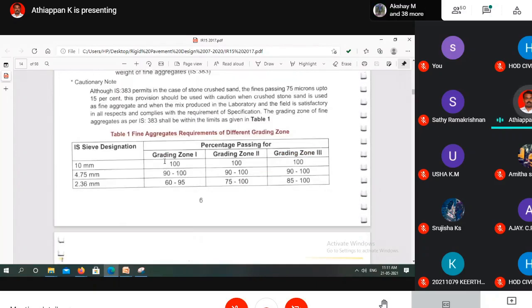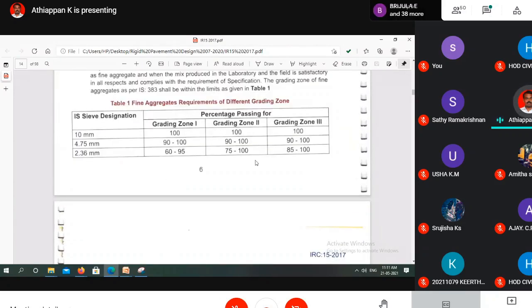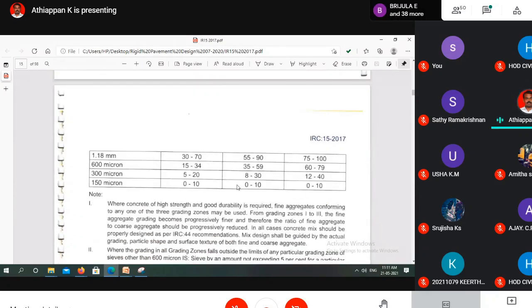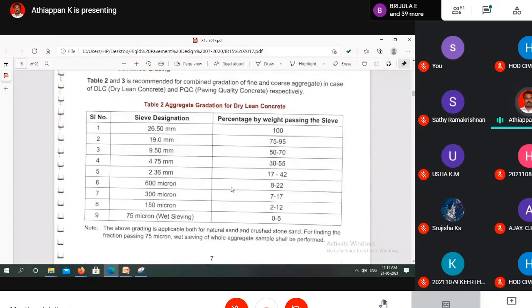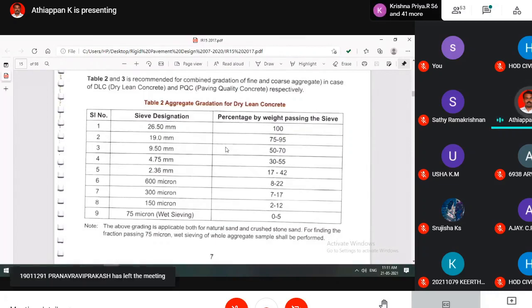See here, this is the fine aggregate which is used for the concrete. So it should satisfy any one of these zones. Okay, then this is the gradation, the particle size distribution record, for the construction of the dry lean concrete. If you are using the dry lean concrete, the aggregate should satisfy this requirement. So in the particle size distribution, in the 26.5 mm sieve, it should pass 100%. Then in the 19 mm sieve, the particles should pass 75 to 95%. Okay, so this is the requirement.